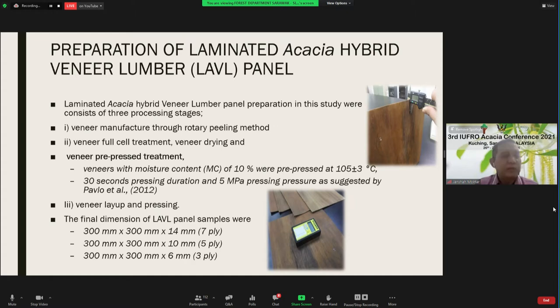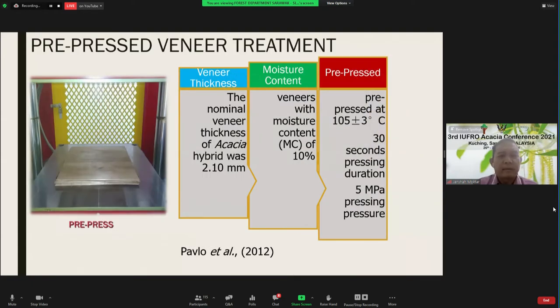In this research, the prepress of the Acacia hybrid veneer was carried out at 105 ± 3 °C for 30 seconds and at 5 MPa, as suggested by Pavlo et al., 2012. For the next slide, we can see the prepress veneer treatment method applied for this study according to Pavlo et al., 2012.